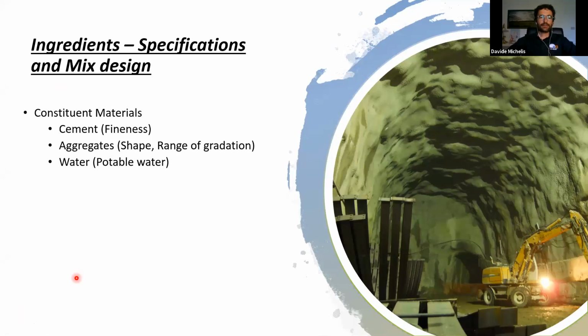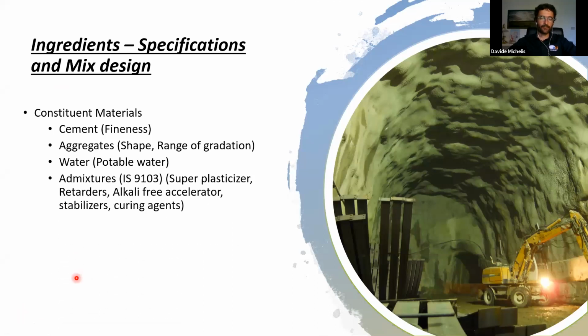Okay, aggregates, different shapes. It depends if it is crushed aggregates or if it comes from a riverbank. Water, of course, we need to put water, especially tap water, as much as possible in order to get a high quality mix design. Admixtures are to be placed inside the mix design during the production process, and also like the accelerators, to be introduced in the mix design during the application, right at the nozzle before the product flows out from the boom of the spraying machine.